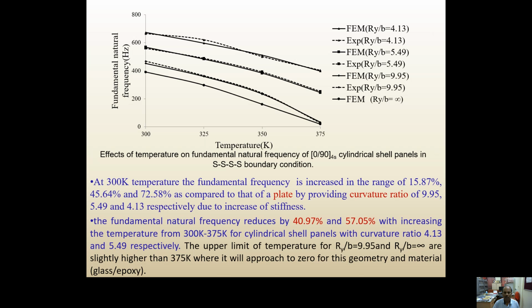Coming to numerical and experimental results. So this is a simply supported cylindrical shell panel. Different R by B ratios have been shown. The last one is R by B infinity, which means actually a plate. These are all shells. The frequency is increasing with the increase of curvature, R by B, of the panels and decreases with the increase of temperature. All the frequencies are decreased with the increase in temperature. The temperature has been increased from 300 to 375 Kelvin.